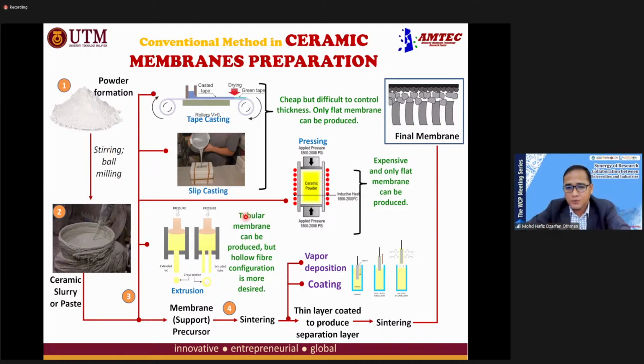After we produce the support, we need to deposit the layers one by one. We can use either vapor deposition, dip coating, or spray coating in order to produce the thin layer on top of the support layer, followed by sintering. And this process will be repeated until we get the asymmetric structure.